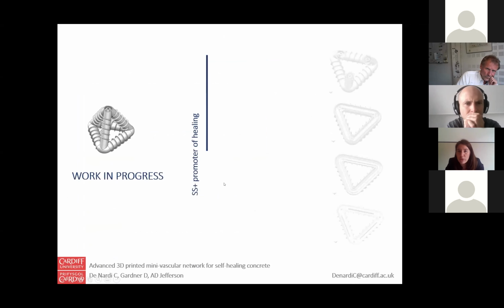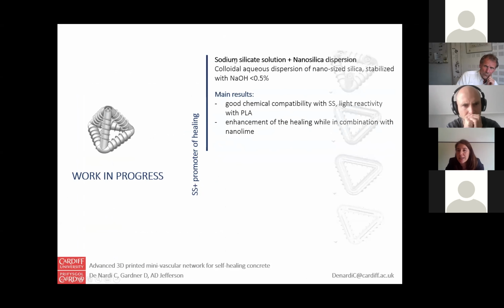So an alternative approach would be to add a promoter of healing when the healing agent remains the sodium silicate. We tested different solutions actually. One is a nanosilica dispersion, a colloidal aqueous dispersion, and it's stabilized. The idea is that both components are compatible with the matrix and with the sodium silicate. However, it seems that the solvent reacts with the PLA.